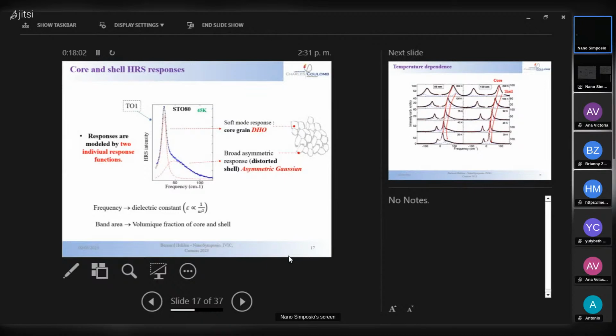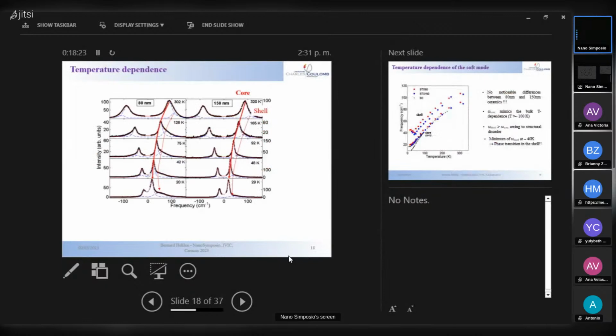So the frequency of this mode directly relates to the permittivity. The frequency here and the frequency there correspond directly to the permittivity, and the band area corresponds to the volume fraction of core and shell. So we have a lot of information in the spectra concerning the dielectric properties. So we made the temperature measurement here.